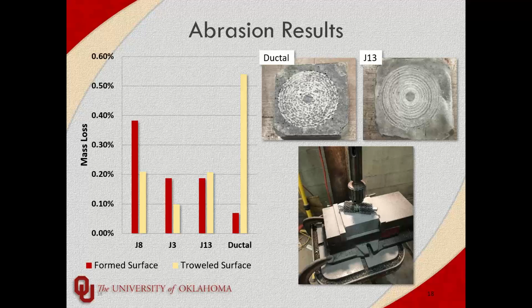But one thing to note, and I think is maybe a slight benefit for our mixes, was the trowel surface, which is just the open surface on the top. It was a lot more bubbly with Ductal than it is with our mixes. There's something about Ductal that causes a lot of the free airspace inside of the mix while it cures to come to the surface, so that you get this friable surface at the top. So that's why Ductal has a requirement for their mixes, in that you have to grind off the first, I believe it's a 1/4 inch, maybe 3/8 of an inch. So whenever you pour it, you have to pour it high and then grind that top surface off, because you get all those extra air bubbles up there.